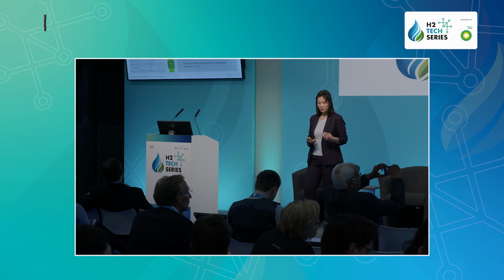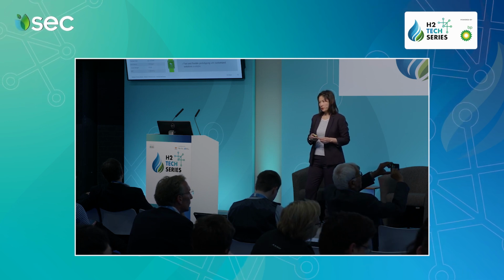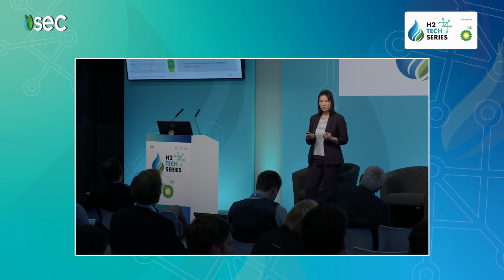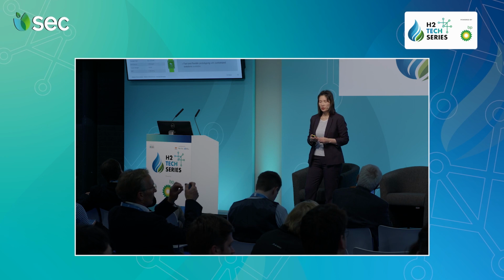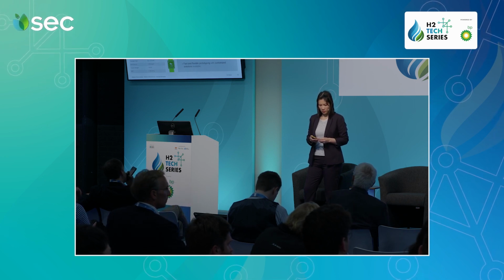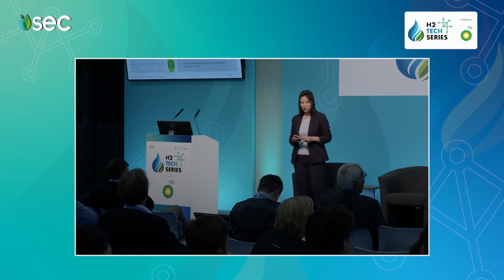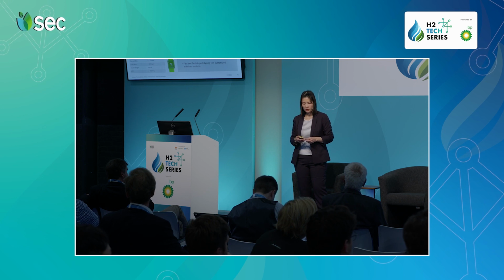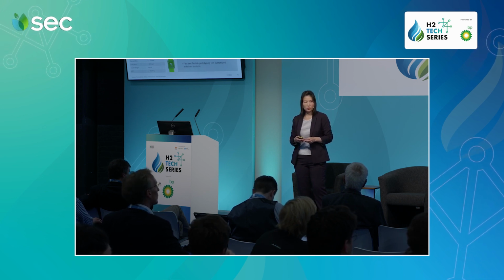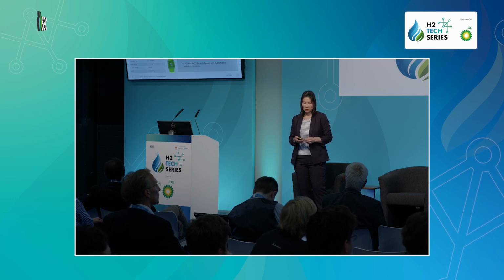The standard size of this catalyst is 2 millimeter. But if you have a bigger reactor, you will need a bigger catalyst. We also can change the carrier depending on your request. The bulk density is around 500 kilograms per cubic meter. The crush strength is bigger than 18 newtons. The BET is 200 square meters per gram.